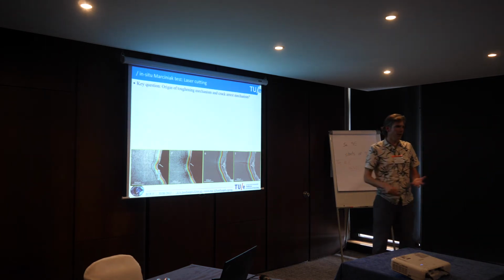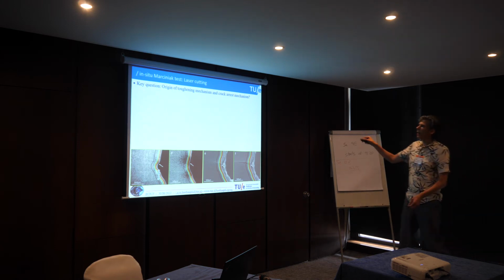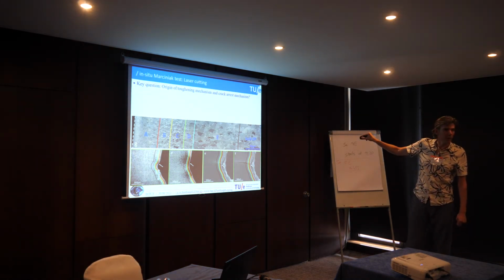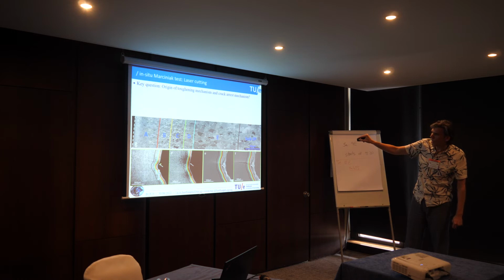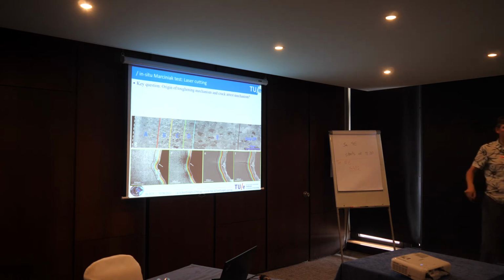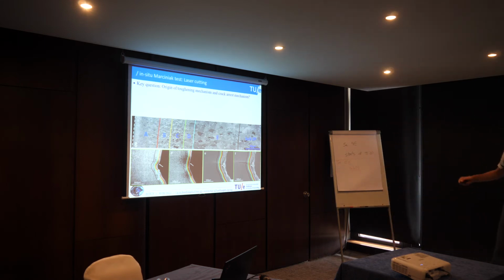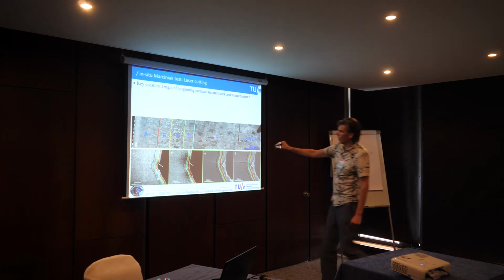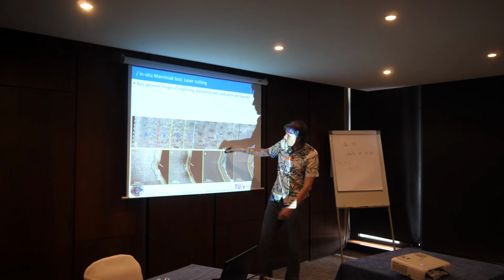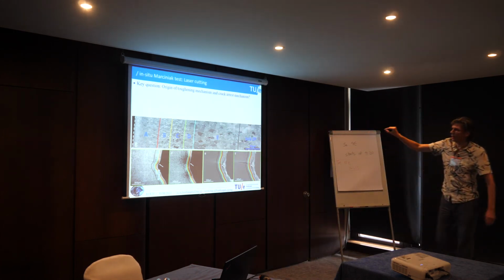But there must be a toughening mechanism at play, right? Like what's happening there? Well, this of course has to do with all these different microstructures. This first damage occurs exactly in the zone where we have the fully martensitic layer, and that damages very easily. But then if you look in time, the damage develops, but it really is being arrested. And the reason is that we have this very tough layer here.